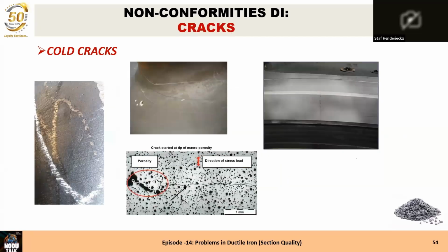So cold cracks, you can see them much better. They are mostly closed, much more closed than hot cracks, and it has to do with lack of shrinkage. It has to do with heat treatment. It has to do with stress during the cooling and in the mold, so that it hinders the shrinking and it cracks. You can see it there in the bottom. You had the porosity over there, and from there on the crack starts, and it's a stress crack.